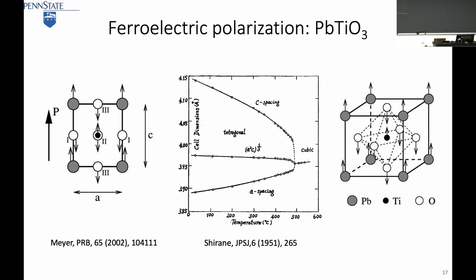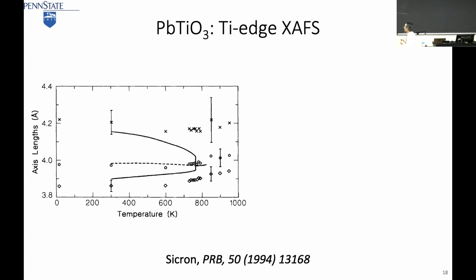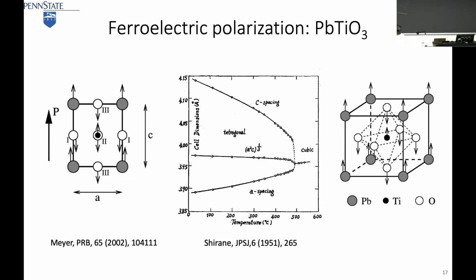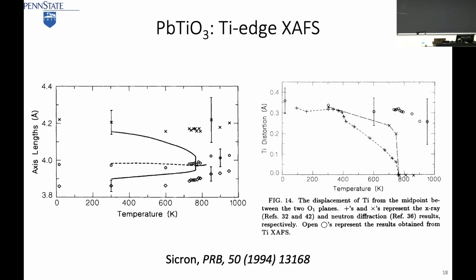Perfect. But there are always some scientists that say this is not quite accurate. So in 1994, there was one scientist that used X-ray to measure the titanium environment. What they found is that you get the lines here from the X-rays as shown before, but the cross symbols, and this diameter, are from these X-ray absorption measurements. So titanium never goes to the center. And it's always at the tetragonal position. And then the next is also tetragonal. And then you measure the polarization too. You find that the titanium is always displaced. Not only tetragonal, but also polarized. So that means if you do X-ray diffraction, you find it's not polarized, it is cubic. If you do X-ray absorption, it's polarized, it's tetragonal.